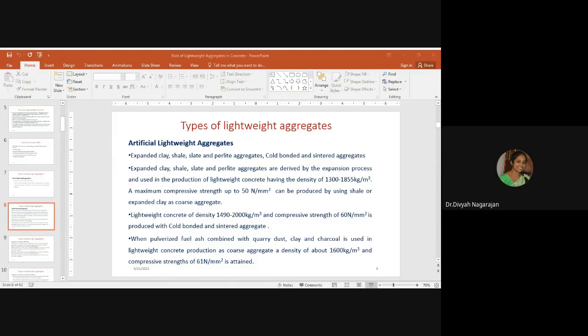They are porous in nature and larger in size, and the lightweight concrete produced from this type of aggregates has a compressive strength ranging between 5 to 33 Newton per mm square, and a density ranging between 1090 to 1415 kilogram per meter cube.